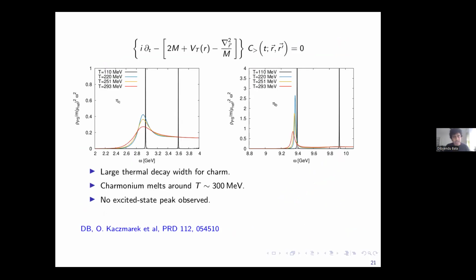Using this potential, now we can get the spectral function. Here is the example of the spectral function that I showed as a cartoon plot earlier, and this is the zero temperature peaks of the spectral function. This is for eta c, with the 1S and 2S, and this is for bottomonium, eta b, 1S, 2S, and so on. We see that once we go to finite temperature, the excited state peaks are all gone, both for eta c and eta b states.